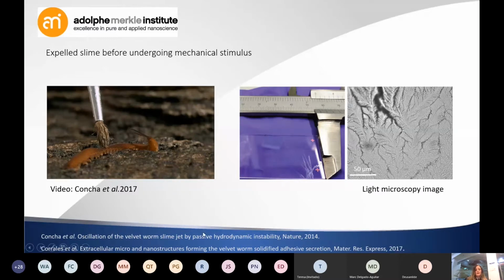So in parallel, people from other countries and us, we publish about this material. We wanted to understand how this material works, why this material dries so fast, and what is going on. Because it's important for molding on demand when you want to produce material with biodegradable materials that we extract from all these natural sources. So how do we mold, because normally all proteins or many other carbohydrates degrade with temperature. So this animal expels this material, and it gets molded and gets the shape of the animal at environmental temperature and at normal pressure. So how can nature do this without degrading the material?